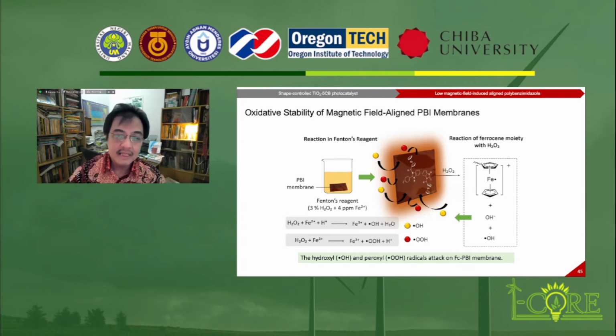In short, we can say that the presence of ferrocene can promote polymer degradation by oxidation reaction. This schematic diagram shows the hydroxyl and peroxyl radicals attacking the ferrocene polybenzimidazole membrane in the Fenton reagent solution. We know that the Fenton reagent solution contains iron and hydrogen peroxide, and radicals are continuously generated from the peroxide via iron cycling between the two oxidation states here. So the generated radicals will readily attack the polymer in the membrane. That is one of the weaknesses of using ferrocene as the aligning agent in this research.